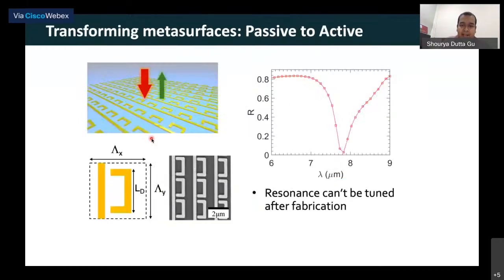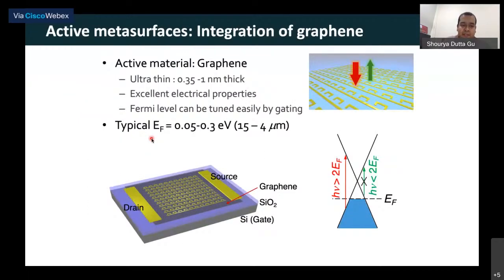Now, if I integrate a layer of graphene, which has very interesting properties, as you might all know, and which people have used for various applications, from batteries to sensors to lubricants, in this particular study we are using graphene to change the carrier density and thereby control the resonance of our structure. Graphene is a sub-nanometer thick layer of sp2 hybridized carbon. It has excellent electrical properties, and you can tune these by gating or by making a field effect transistor. The way we work with these devices is we have a layer of metasurface placed on a single layer of graphene.